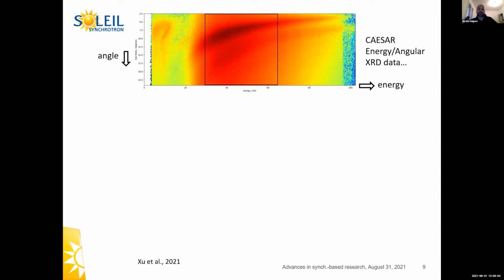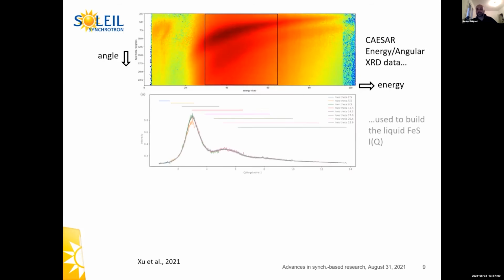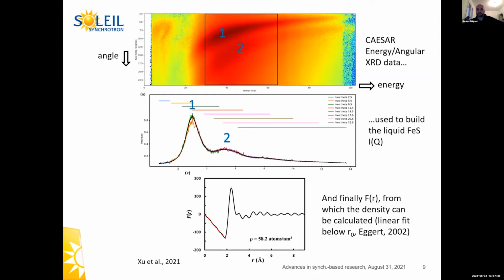This is a typical CAESAR diagram, with on the horizontal axis the energy, on the vertical axis the angle, and you can see on each line an energy dispersive X-ray diffraction. From this data set, it's possible to remove the background and to correct for the intensities to get this I of Q. Here it's measurements done on liquid iron sulfide, measurements done by Xu and collaborators, published this year. And you can see the first two bumps of the liquid on the diagram and on the I of Q. And finally, from this I of Q, it's possible to get the G of R and F of R, from which the density can be calculated thanks to the linear fits below R0 following the method developed by Eggert and published in 2002.